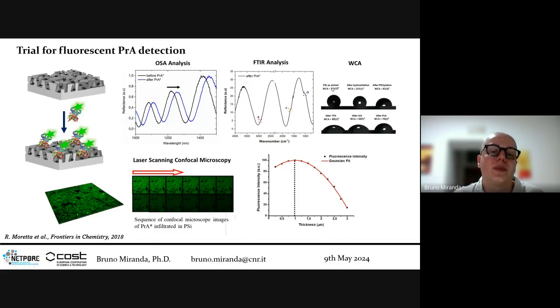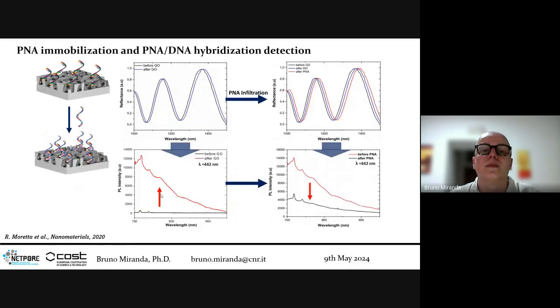We also checked, to verify the functionalization with graphene oxide, using labeled protein A with confocal microscopy to confirm the protein A was inside the pores. Since the thickness of our membrane is 2 microns, we have a maximum around 1 micron. This confirms that like protein A, the graphene oxide was also inside the pores.